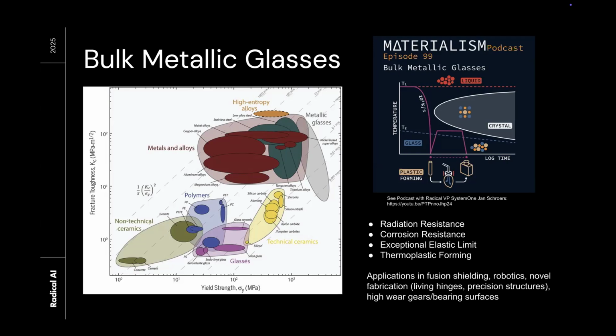So often in alloys, the properties are dominated by the microstructure, which doesn't exist because you have a fully amorphous phase, and the presence of grain boundaries, the presence of dislocations, all these sorts of things. So you get various properties for free. Because you have a disordered structure, your radiation resistance is good because you get knocked out of a pseudo-equilibrium position and then you relax back. The difference between an irradiated structure that is damaged and a normal structure is much more minimal. So you can rely on them in engineering scenarios.